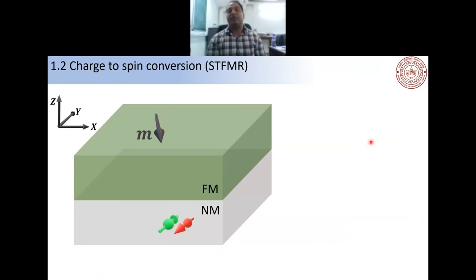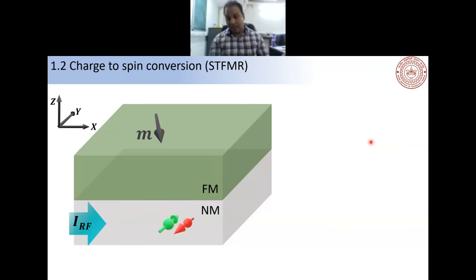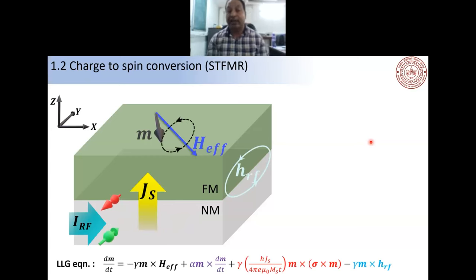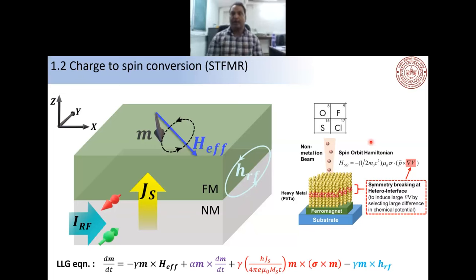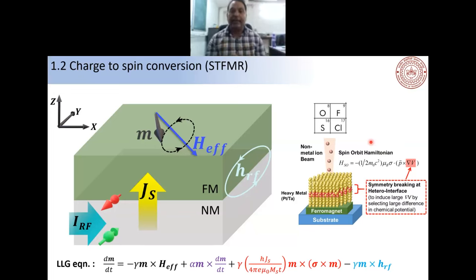We are also building new materials for enhancement of spin-to-charge and charge-to-spin conversion in platinum. For charge-to-spin conversion, we use ST-FMR measurements: applying charge current to platinum generates spin current, which exerts a torque on the magnetization and causes precession. We are interested in designing new materials for higher charge-to-spin conversion efficiency, for which we use ion implantation. The standard approach changes the potential gradient to enhance spin-orbit coupling in the heavy metal.